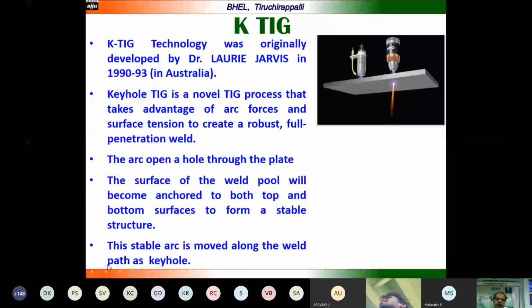It is a novel TIG welding process that takes advantage of the arc forces and surface tension to create a robust full penetration weld. The arc opens a hole through the plate as you are seeing here, and the surface of the weld pool becomes anchored to both top and bottom surfaces to form a stable structure, and the stable arc moves along the path as a keyhole. In keyhole TIG welding, the welding can be done for deeper penetration.